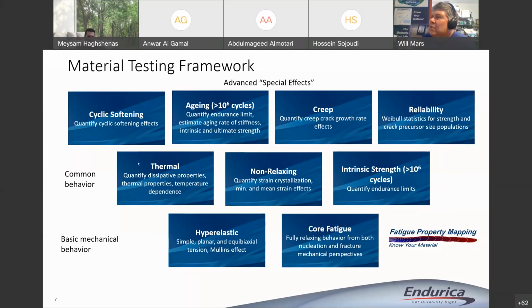Sometimes in certain applications, the thermal dependence, rubber can, if you cycle it fast, it can self-heat. And so sometimes you have to think about that. Sometimes you have to think about the dependence of the crack growth rate law on temperature. So those are things that can be characterized. Under certain conditions, some rubbers will exhibit an effect known as strain crystallization, which results in a strong mean stress benefit. So in certain rubbers, if they crystallize, if you increase the mean stress, that promotes crystallization, which in turn increases the fatigue life of the rubber. It's kind of a mind blow.